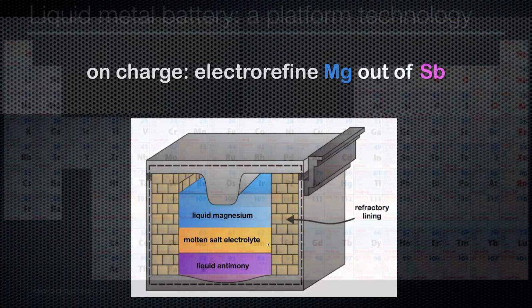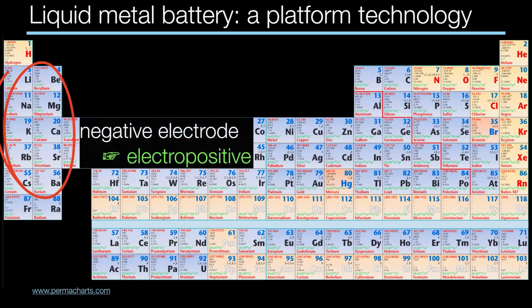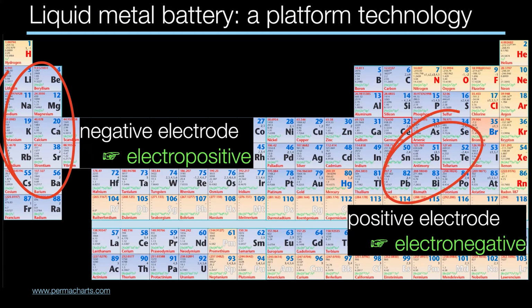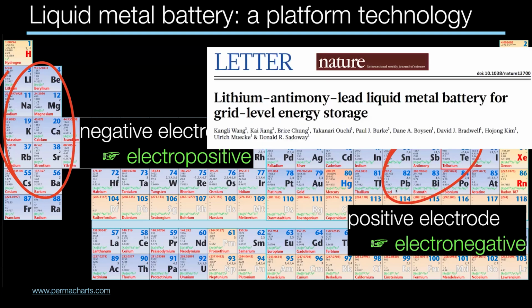and restores the magnesium on top here to its initial pristine condition. And so this was one example, but we had a plurality of candidates for the upper electrode, the negative electrode, some people call it the anode. And so all of these are candidates, and we did work with them. We worked with lithium, we worked with sodium, we're working with calcium right now. And there's a plurality of elements for the positive electrode, for the cathode. So I showed you antimony, but we've worked with lead, we've worked with bismuth. Obviously, we wouldn't work with tellurium because it's only as earth abundant as gold. But if you wanted to be silly, I suppose you could build one like that. So there's a plurality of choices here. And again, a paper in Nature. This was 2015, I believe. And so this again is to show that this work was of high quality. It wasn't just cook and look.